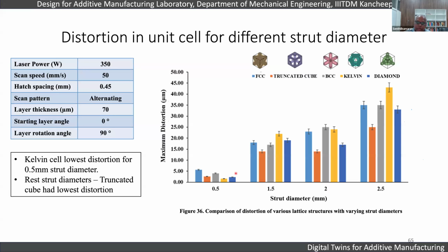As is obvious, we have found that the maximum distortion is for larger strut sizes, because size effects are always going to increase the stresses. For smaller sizes, like 0.5 mm strut diameter, we found the minimum distortions, but strut sizes larger than 2.5 mm had a very high distortion.